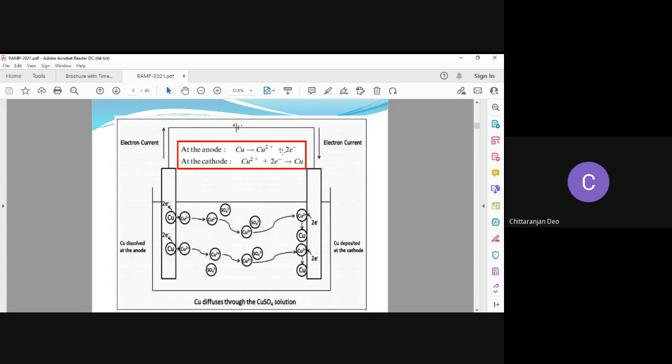The impure copper anode is dissolved and hence reduced in mass. The insoluble impurities collect under the anode. No other reaction takes place at either electrode as copper is less reactive than hydrogen.